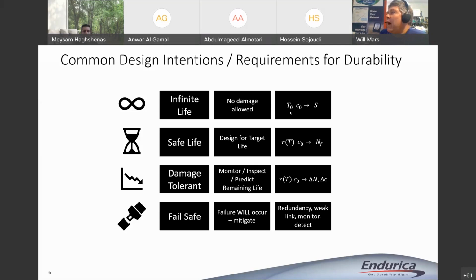Now, in order to apply this, you need to know what that limit is, and you also need to know C naught. C naught is the crack precursor size, right? All materials contain initial cracks in the microstructure, and so if you're working with rubber, and if you know this fatigue limit, if you know the precursor size, that puts you in a position to calculate basically a crack driving force, right? An energy. If you've taken fracture mechanics, energy release rate is what we use. And you can compare your energy release rate to that fatigue limit.